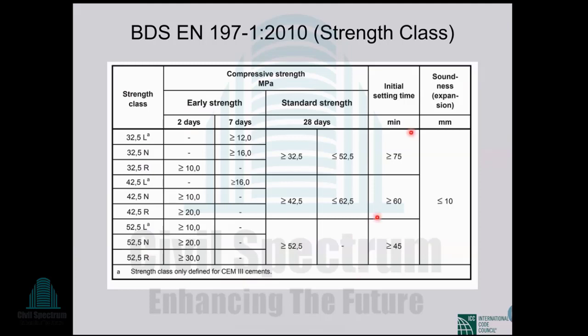And in terms of setting time, there is a lower limit for initial setting time. For the 42.5 strength class, the initial setting time must be more than 60 minutes, not 45 minutes that we usually know. Usually, the cements that are available in Bangladesh all comply with this. And for the 52.5 strength class, it must be more than 45 minutes. So the cements available in the market easily comply with these conditions.